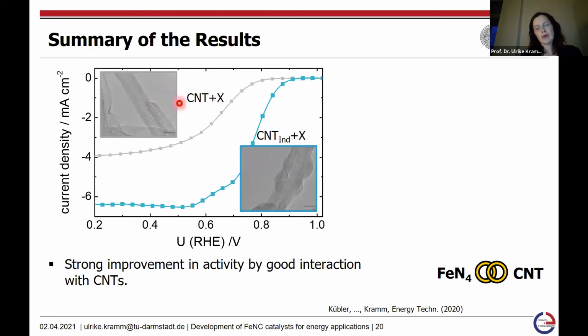First of all, when we were looking at the TEM images, we were able to see that here we basically see a CNT, and then somewhere beside it there is the carbon framework with the FeN4 centers integrated. But for the surface-functionalized CNTs, we get these carbon frames directly attached to the walls of the CNTs. This becomes also visible when you zoom out. Then you can really see that all of the CNTs look like they have these kinds of spots on their surface. These are the results from an RDE experiment, and in that case, you have the current density as a function of the potential.